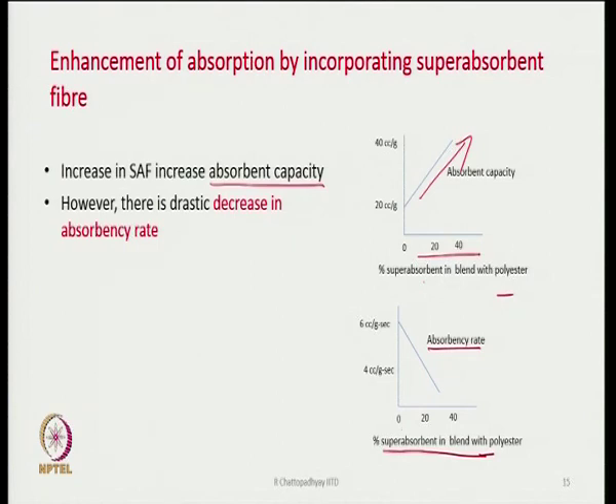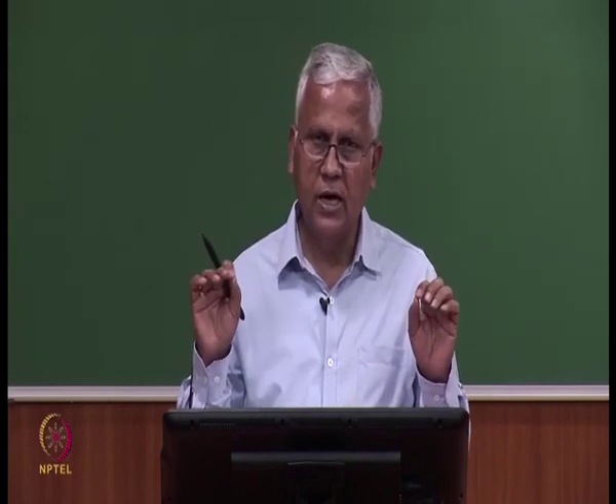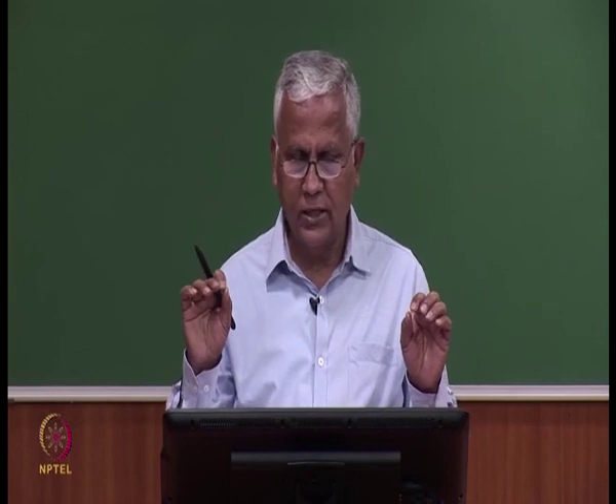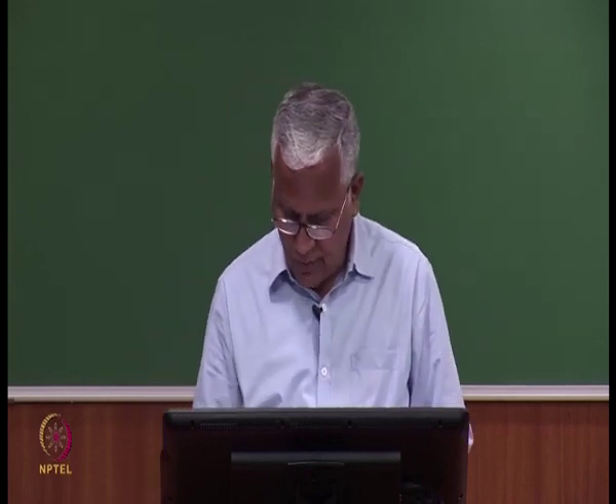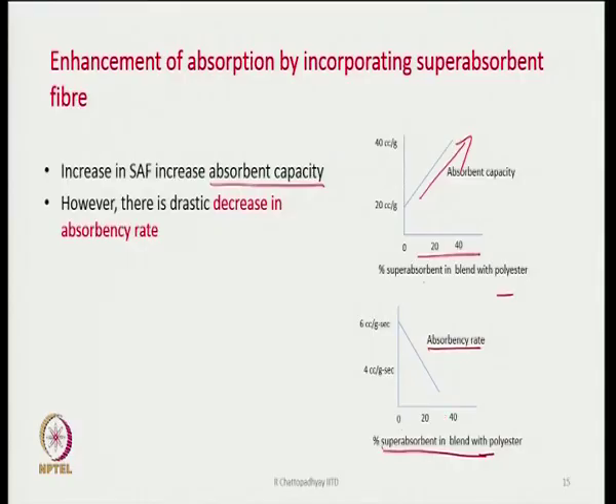Because it transforms itself into a viscous liquid, under pressure this liquid will not move so easily, because its viscosity has become very high in comparison to water. If the super absorbent polymer changes itself into a viscous liquid, the liquid will not be able to flow so easily. The way water flows, this viscous liquid will not flow so fast. Therefore, it can hold the liquid very easily without leakage. That is the advantage we get, and hence one has to very judiciously use the percentage of super absorbent fiber. So, that way we need to use them.